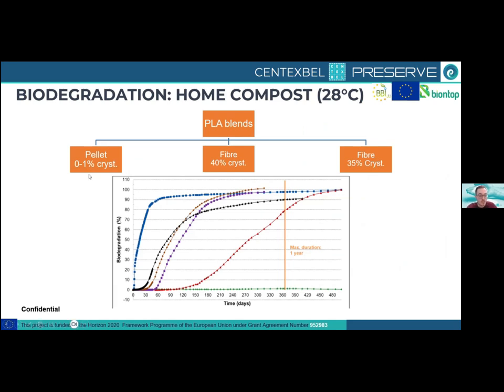What is important to mention is the crystallinity, because the level and the speed of biodegradation is really comparable with the crystallinity. The more crystallinity it has, the less fast it will biodegrade. When you look at just the pellet version of the material, so not when we stretch it, it has very low crystallinity, and it will have a much faster biodegradation. But when we go to the fiber, which has 40 or 35% crystallinity, depending on the settings that we use, we get a less fast compostability and biodegradability, and this we can tailor by using different types of polymers, different blends, different ratios, etc.